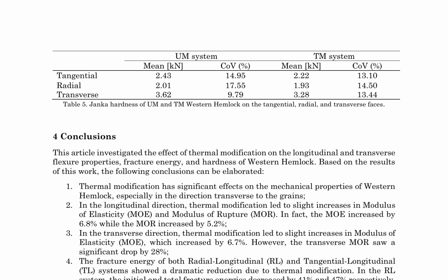The Janka hardness values for unmodified and thermally modified (TM) Western hemlock are presented in Table 5. On the tangential face, the mean Janka hardness values for unmodified and TM Western hemlock are 2.43 kilonewtons and 2.22 kilonewtons, respectively, with coefficients of variation (COV) of 14.95% and 13.10%. Similarly, on the radial face, the mean Janka hardness values are 2.01 kilonewtons and 1.93 kilonewtons, with COV of 17.55% and 14.50%. On the transverse face, the mean Janka hardness values are 3.62 kilonewtons and 3.28 kilonewtons, with COV of 9.79% and 13.44%. The conclusions drawn from this study are as follows.